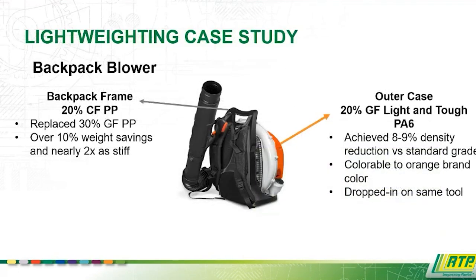So let's take a look at a little case study using some of these lightweighting techniques. Here's a backpack blower. This is obviously something that's going to be very sensitive to weight, with the worker carrying that around all day. We worked on a couple parts in this application, including the backpack frame. We replaced the 30% glass fiber polypropylene with a 20% carbon fiber polypropylene. There's over 10% weight savings, and the part was nearly 2 times as stiff. So weight savings and improved stiffness and performance.